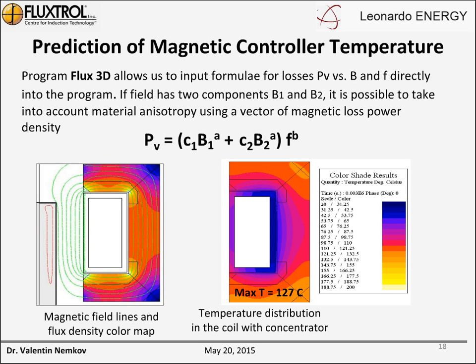The best magnetic and thermal properties are in the plane perpendicular to the direction of pressing, and the minimum in the direction of pressing. On the left picture, you have magnetic lines and flux density map, and on the right side is the temperature. And for this very practical case, we calculated and then proved that it's correct. Maximum temperature slightly above 120 C, which is a very good number for materials that typically tolerate up to 250 C.